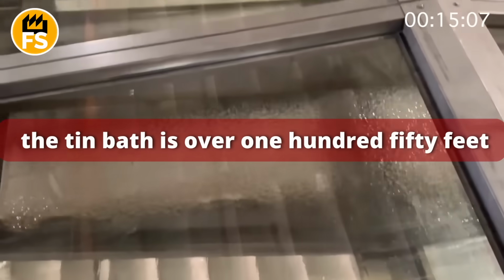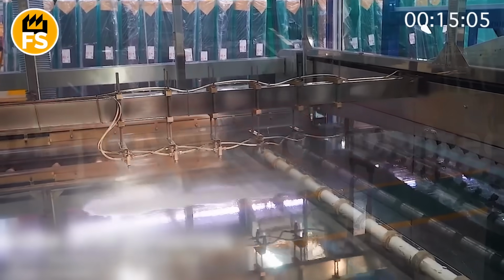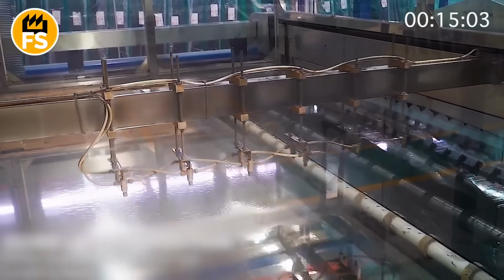The thickness is controlled by stretching. Special rollers or electromagnetic fields stretch, or conversely, compress the glass ribbon. This way, you can get glass with a thickness from 1/16 to 3/4 of an inch, depending on the client's needs. The length of the tin bath is over 150 feet, and the glass slowly floats along it at a speed of up to 25 feet per minute, cooling along the way to 1,000 degrees Fahrenheit.